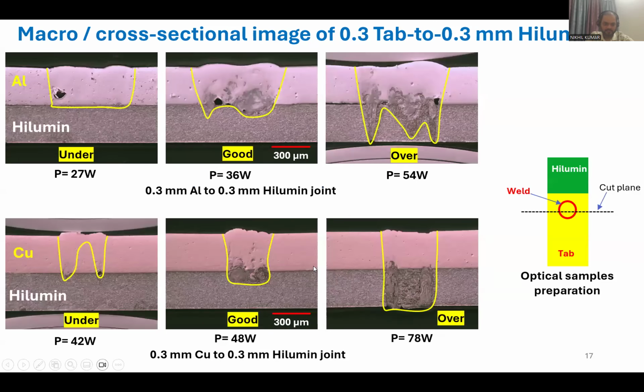And this is also reflected in the joint strength as well. For this particular combination, you have seen very low strength, because this one was showing about 200 Newton load, and this one was showing about 500 Newton load. And this one was also showing very low strength. I think it was about 200 to 300 Newton load, and this was showing 700 to 800 Newton load. You can significantly see the change in the strength based on this penetration depth and weld width.